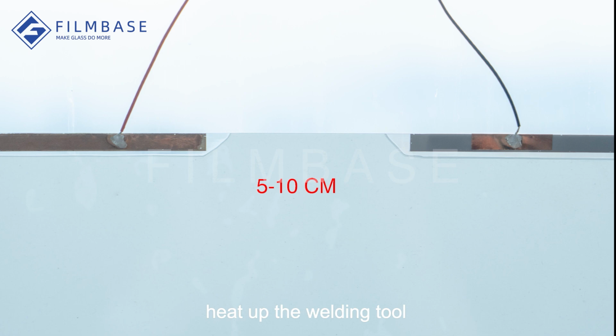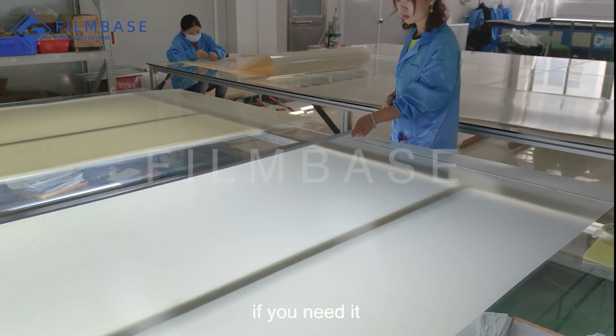Heat up the welding tool and apply the welding wire on the strip to create a bubble welding dot. Prepare welding dots on the copper strip at a distance of 5 to 10 centimeters between the 2 dots. Heat up the dots together with the wire cables and add more welding wire if needed. When cooled off, the cable should be attached and welded together. If the cable comes off or detaches, reheat the dot and add more welding wire if needed.